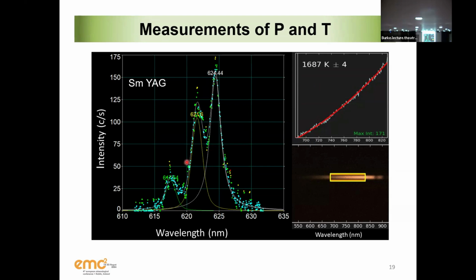And the only way to do that is, I cannot use the ruby, because everybody knows that the luminescence of ruby becomes a very large, broad feature when it's at temperature. So we are using the samarium YAG, which is practically independent of temperature. The YAG doesn't get warm because it's not heated by the laser. It's just in the same chamber, okay?